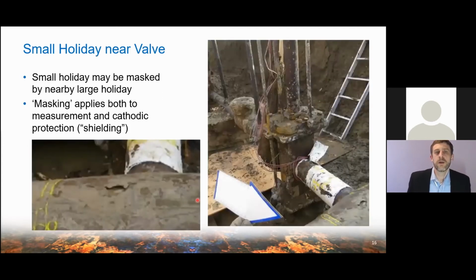Okay, so this is the basic configuration once they dug it up. They've got our pipe here, and then the tee off, and there's this valve. So that cross gradient measurement that I mentioned is going to be very sensitive to the reference electrode placement. Was my reference electrode lined up with the valve? Was it on this side of the valve? Was it past the valve? All of those would result in different cross gradients in my measurement.